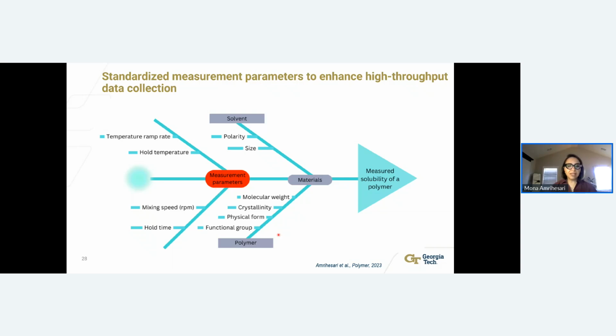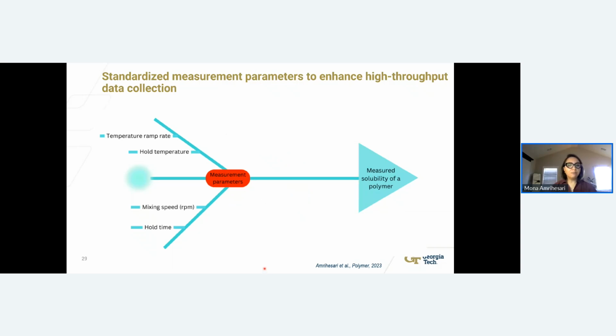So for the next couple of minutes, I will be more focused on the measurement parameters. We did not do anything on the material side, except the fact that we kept the molar mass to a lower value to avoid a lot of kinetic complication. We selected anything that we could commercially buy below 15K on the molar mass, and we only focused on the measurement parameters for standardizing our method, looking toward more high-throughput data collection.